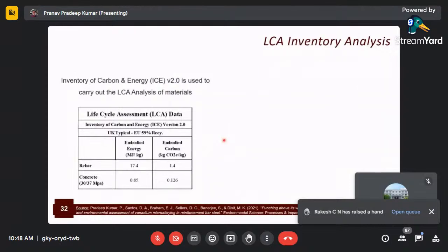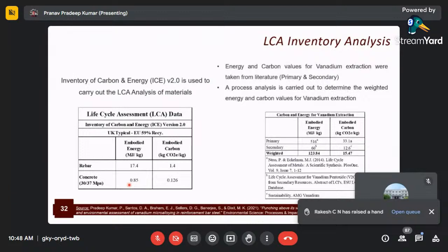And as I mentioned previously, the life cycle inventory that we used here for this study was the Inventory of Carbon and Energy, the ICE database. And you can see how the embodied energy and the embodied carbon of rebar or steel is beyond an order of magnitude as compared to the embodied energy and embodied carbon of concrete material. And for the energy and carbon values of vanadium, both from the primary and secondary production of vanadium, we obtained it from digging deep into different literature sources that are listed down here.